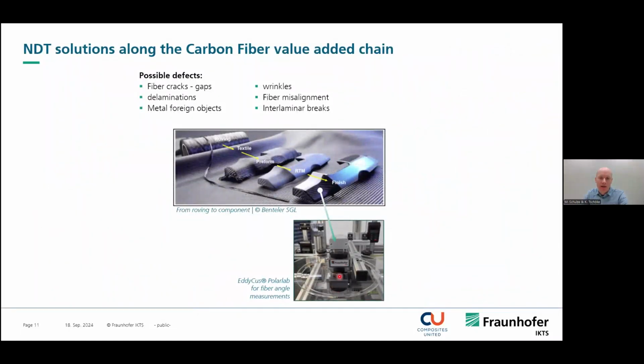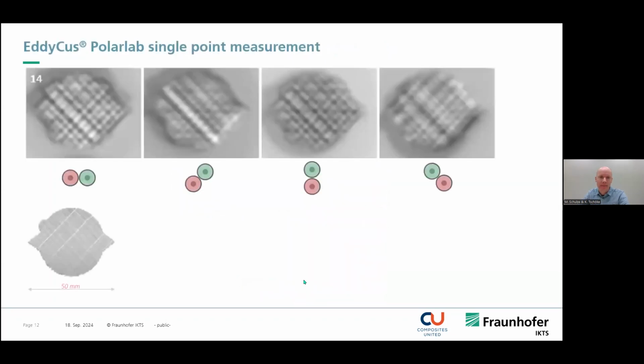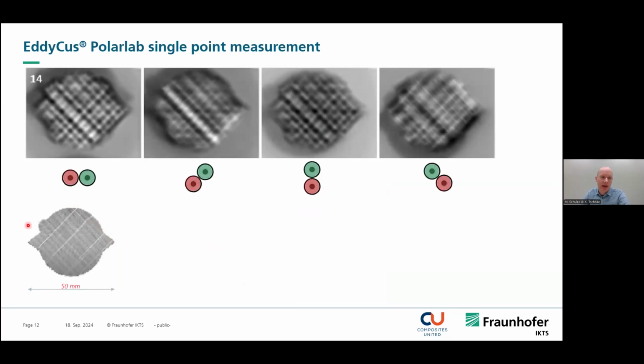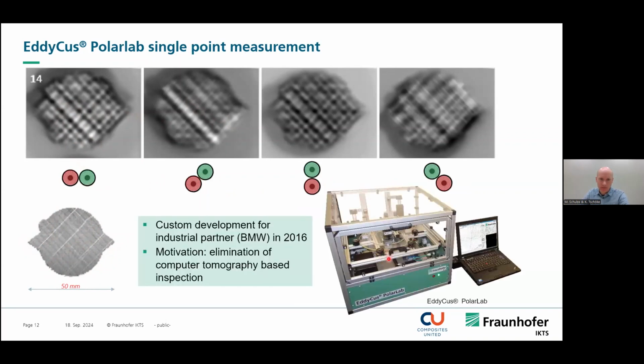To analyze small parts only for their angle or layer orientation, we have this so-called EddyCus Polarlab. It was also developed for BMW, so they had the task to monitor the fiber orientation in these small specimens. Here we see eddy current C-scans acquired with different probe orientations. You see that there is a different behavior in the C-scan when we rotate the probe. And this is the device. We wanted to eliminate the cost-intense computer tomography-based inspection of this type of specimen with this device.